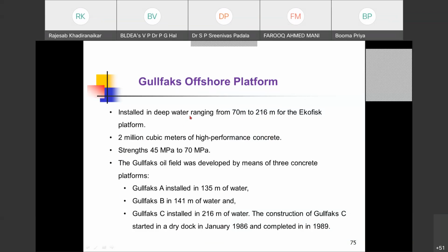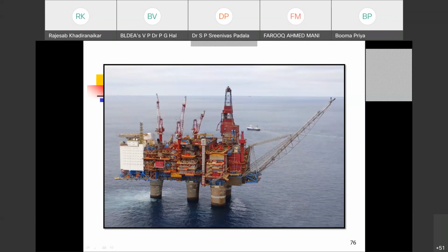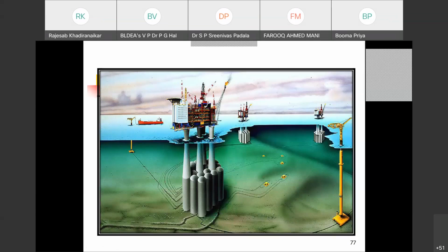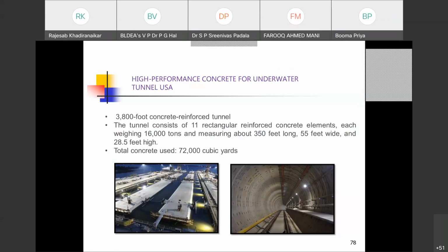This is a beautiful application, Gullfaks offshore platform, an oil exploration platform, and 2 million cubic meter of high-performance concrete was laid in this, with the strength ranging from 45 MPa to 70 MPa. This is a beautiful view of this oil exploration platform, and this is the top view and the below water view. And then concrete for underwater tunnels and offshore structures, underwater structures, because the performance is a major issue. The durability is a major issue.